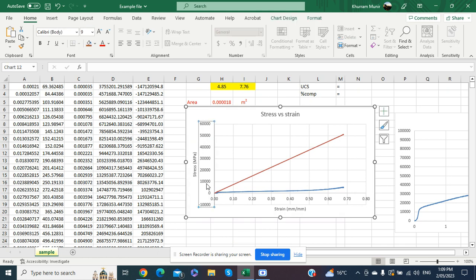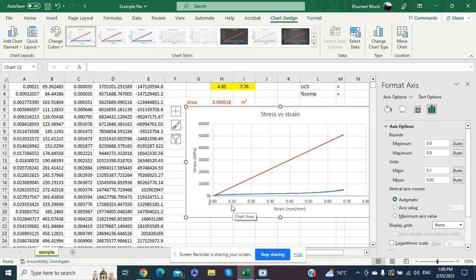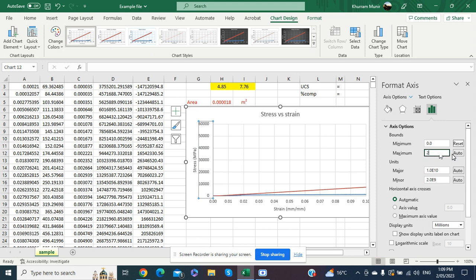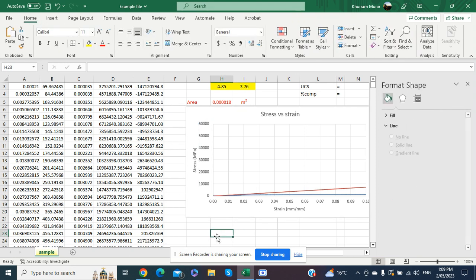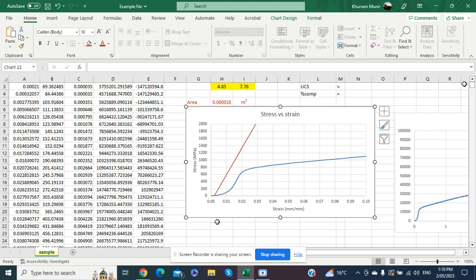Starting from zero, we can see a straight line for the yield strength has been added to the graph. We improve visibility by setting the x-axis from 0 to 0.1 strain. However, we notice the straight line does not start at the correct strain offset — this is a problem with the compression test when force and displacement are not balanced at the start, introducing an error into the data.